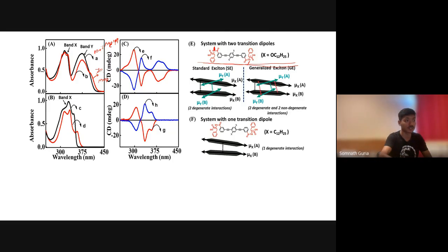This molecule is highly hydrophobic, and whenever we increase the polarity of the solution by adding water, they start aggregating to each other and make a helical structure, which becomes CD active, showing CD activity in the 450 to 300 nanometer region.